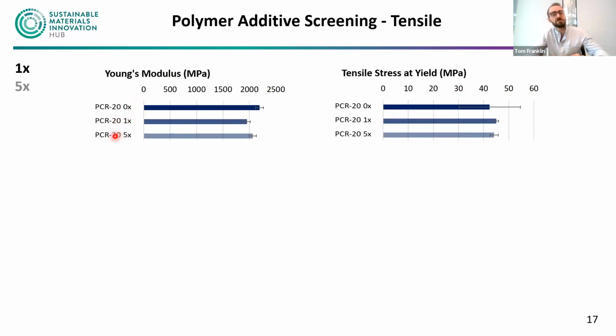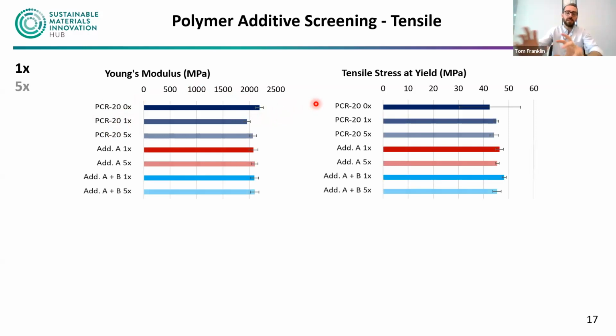So the first grouping on the screen is with no additive. And we can see straight away that nothing really happens. We have some very subtle changes. The most significant change is after one reprocessing cycle, but then not a lot happens, which is surprising given the change in molecular weight that we know occurs. So let's look at the additives. Our antioxidants in the red and the blue. In both cases, and for both graphs, we see virtually no change, which again, when we think of the molecular weight, would fit. We're not changing our molecular weight, so the mechanical properties should stay the same.